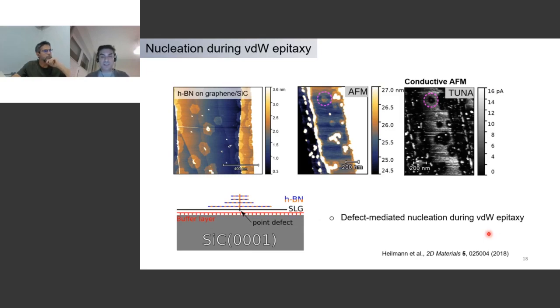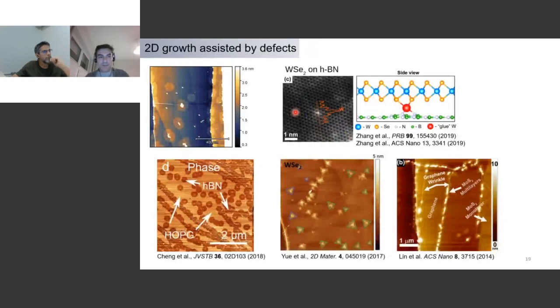In other words, we don't have an ideal scenario where, as I explained before, just van der Waals forces are dominating, but we probably have some strong bonding there, maybe covalent bonding, that is happening, and it's leading to the nucleation. And the problem with that is that, first, this seems to be happening in a general manner. It's not only related to HBN on graphene, but there are other examples in the literature.